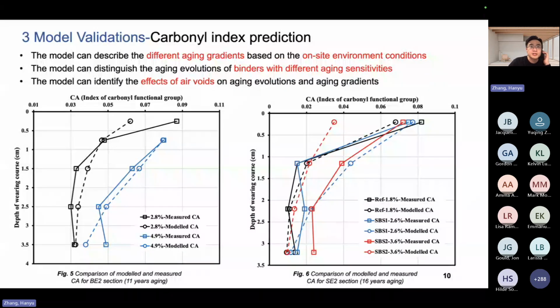The next part of validation is about the carbonyl index prediction. So this slide shows the comparison of modeled and measured carbonyl index, which we use for quantifying aging. So first, we say that this model can describe the different aging gradients based on the site-specific environment conditions. If we have a look at the right figure, it's the modeled aging gradients and measured aging gradients using carbonyl index for different binders used in the same road section.